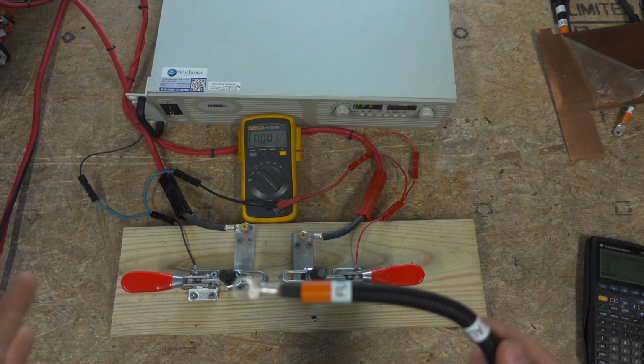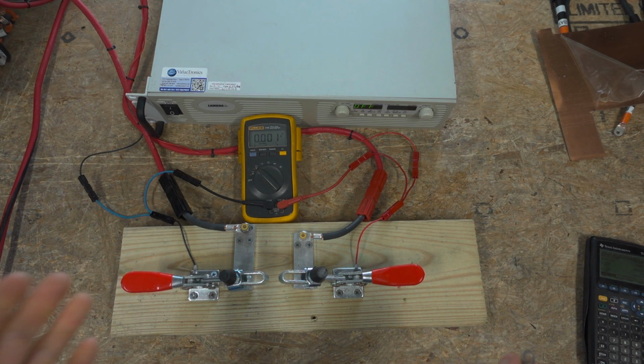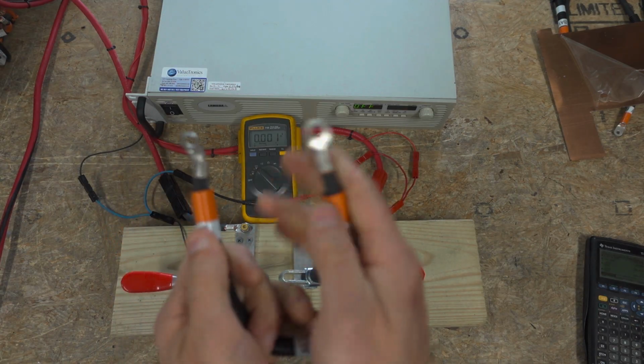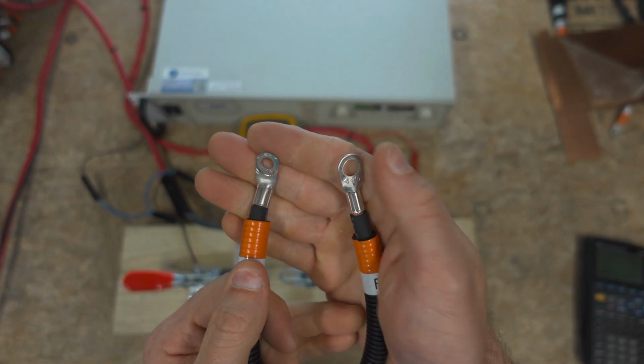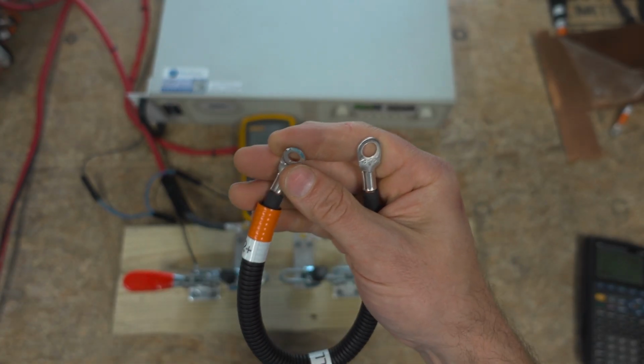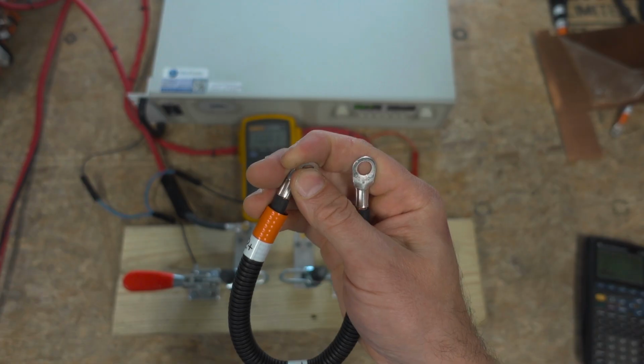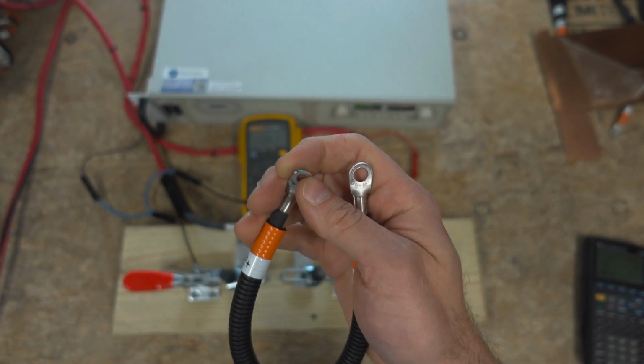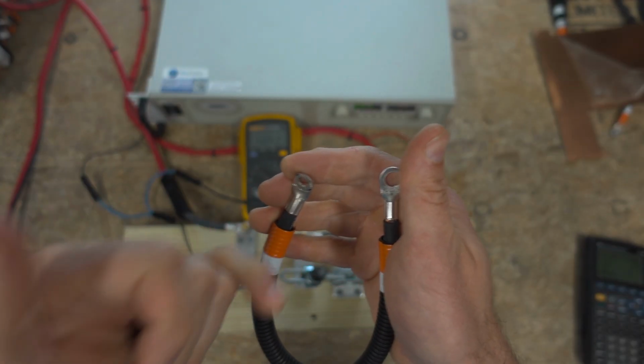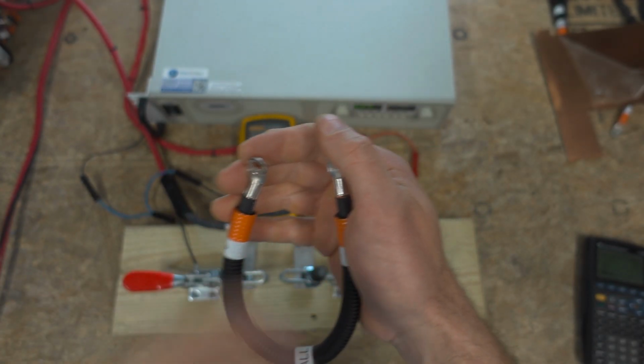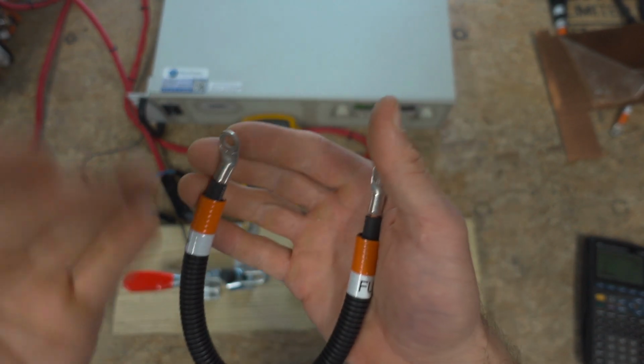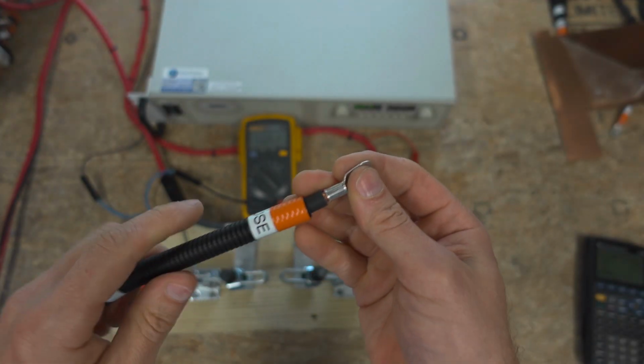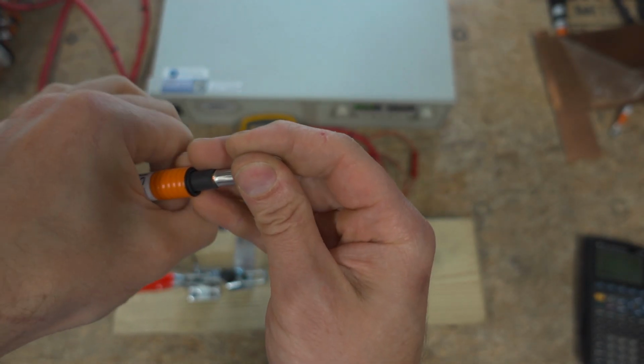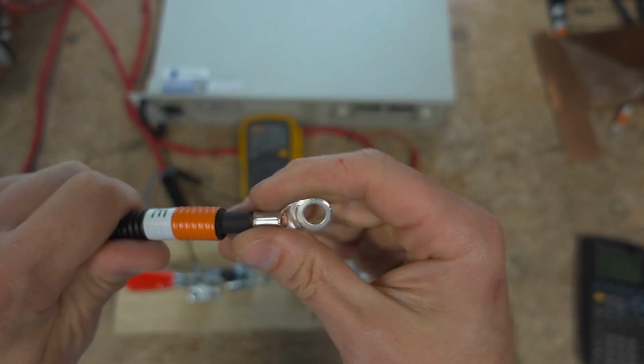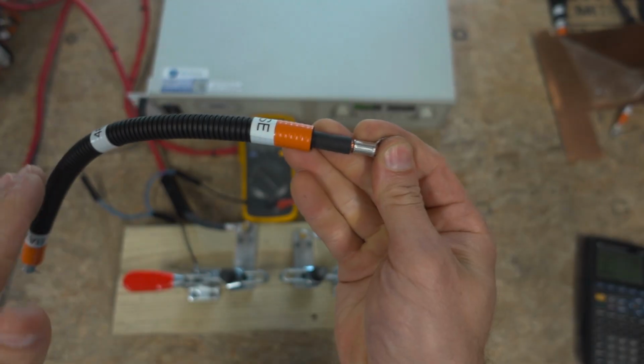It's weird. It's wild to see someone speak to the industry and recommend that soldering automotive cables that are going to see vibration is a good thing. It's not, and you should not do it. There's almost no reason why you would need to do it. Look at industry. Look at all of the assemblies out there. Show me a soldered cable that is not then overmolded, cast in epoxy, cast in plastic, to where there is no vibration. Just putting your cable in a channel doesn't work because you can still vibrate. Unless that channel is then filled with a resin, you're still gonna have local vibration, and you don't want that embrittlement coming down into your copper.